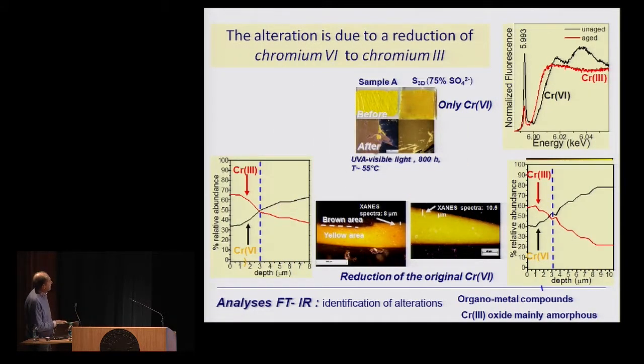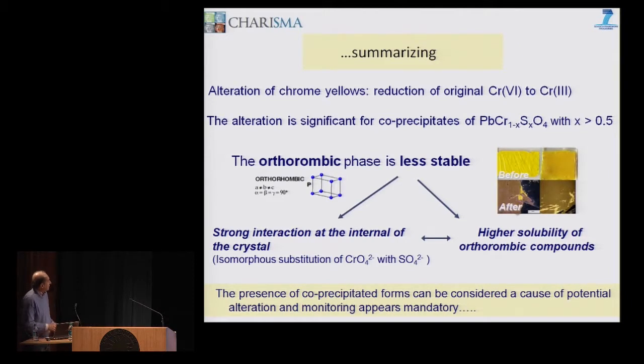And it was possible to characterize, through examination at the synchrotron of the various pigments that were altered, that the alteration consists in a reduction of chromium 6 to chromium 3, with the formation of some chromium oxide that is green, and this explains the darkening, but also some organometal compounds. So, summarizing, the orthorhombic phase is less stable for these pigments, and also those pigments that contain a high quantity of sulfates are more subject to the alteration.